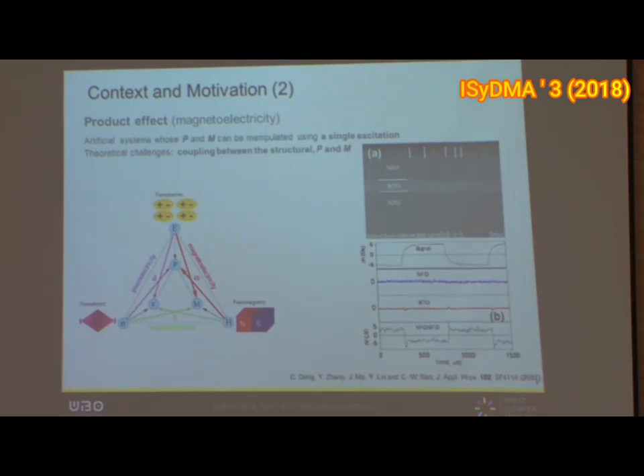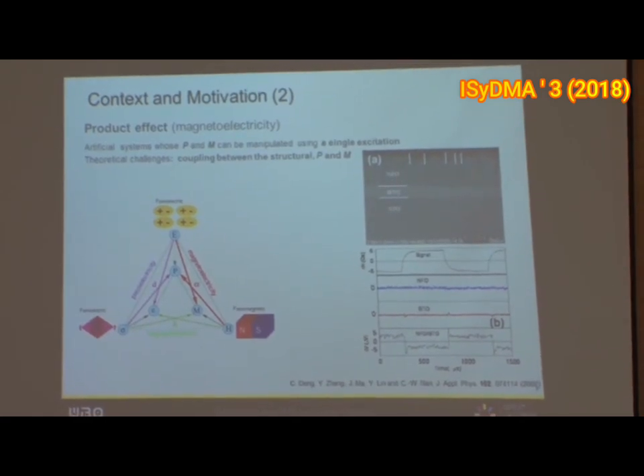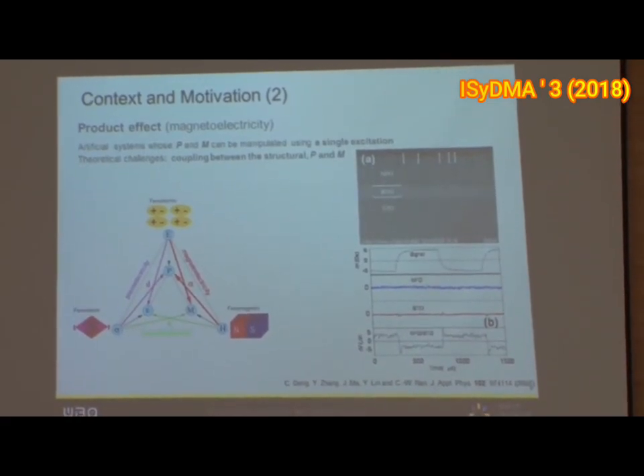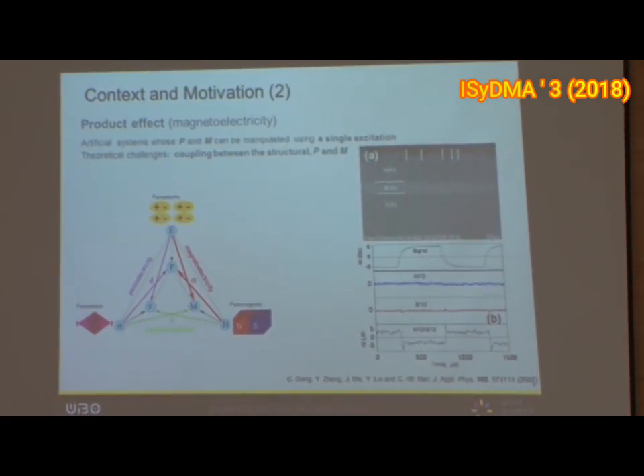But when the two thin films are in series, you can clearly measure signals, which is proof of principle that you have realized cross-coupling between the polarization of the barium titanate and the magnetostriction of the iron oxide. This result was the first proof of principle of this effect.